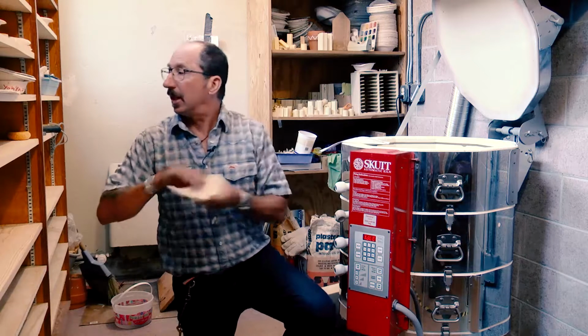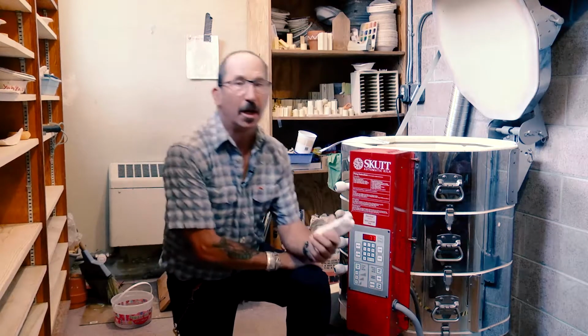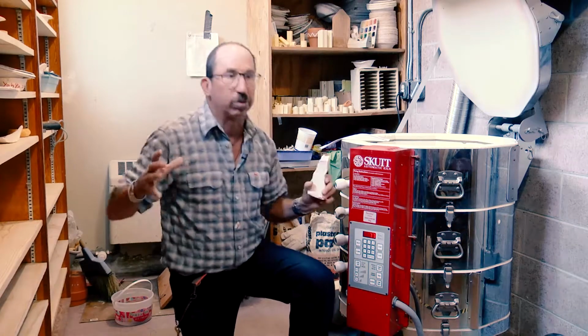Essentially, if it's a thick piece like this here that's very solid, maybe 1 inch thick in places, normally I would preheat this, and by preheating I mean keep it below boiling point. Just like your pasta water, you're watching it, it's not boiling yet, it's getting hot, but before it boils, it's evaporating and the molecules aren't jumping around. When the water inside clay boils is when it explodes the piece. So as long as we stay 200 or below, boiling point is 212, we will drive the moisture off without activating all those molecules into that expansion mode, which then says blow up.